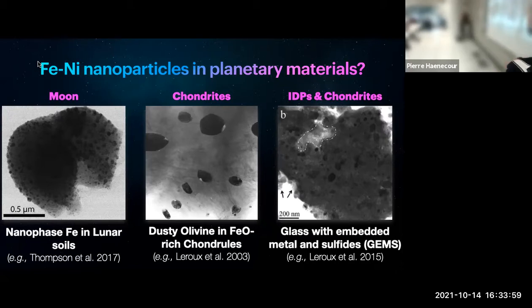And then the last example that we have is what we refer to as GEMS grains, which is glass with embedded metal and sulfide. Those are found in material that we think comes from comets, in particular interplanetary dust particles. They show those really large areas. I mean, for us it's very large, it's probably not large for you. It's several hundred nanometers inside of a glassy matrix, with a composition similar to magnesium silicate, but amorphous magnesium silicate, with those embedded iron nickel particles and some sulfides. Those are basically the three main environments where we have been observing those iron nickel nanoparticles so far.